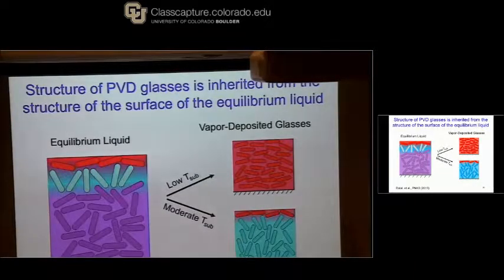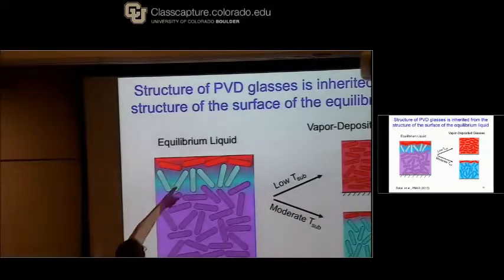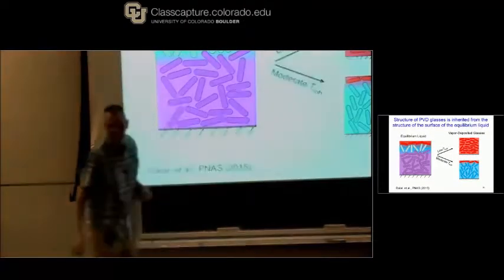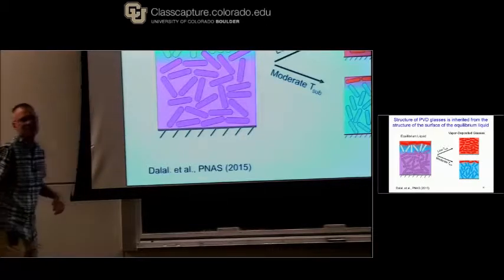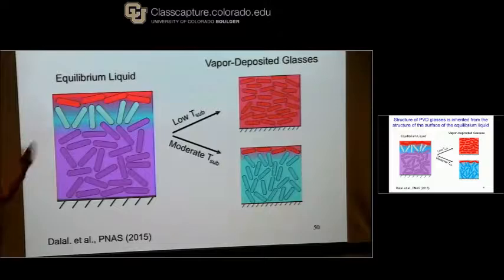Okay? And what this plot illustrates is that right at the free surface, there's a tendency for molecules to be lying flat. Just below that, there's a tendency for molecules to be standing up. And in fact, it probably would have been better if these standing up ones were poking through and also touching to the same distance. That would be a more realistic representation of what's in the substrate. Okay, so any of you can do this. You can go run your own simulation of an equilibrium thin film of anisotropic objects. And I think if you choose objects that are this shape, this is what you're going to see, because we've tested it with some more coarse-grained models, and this is what we commonly observe.